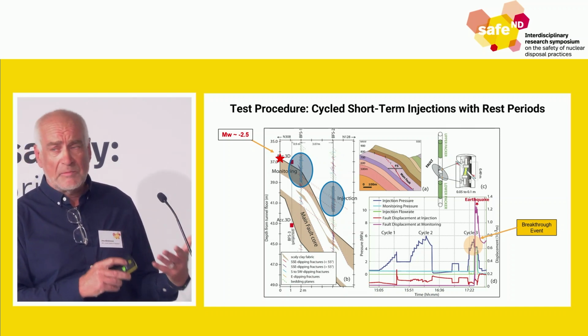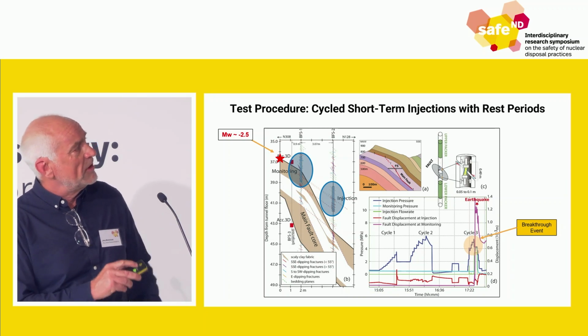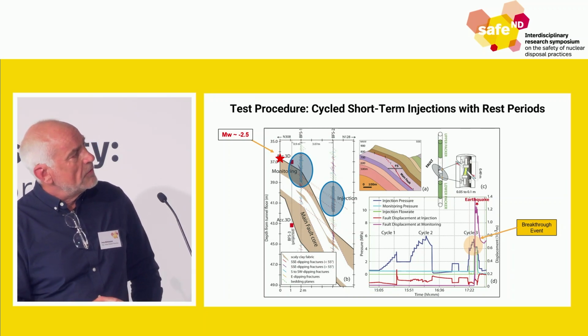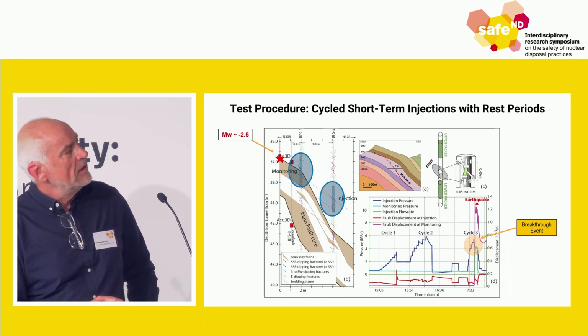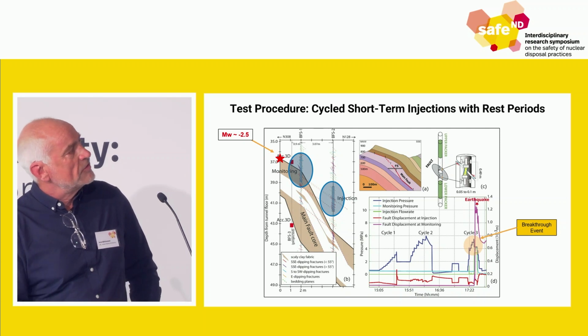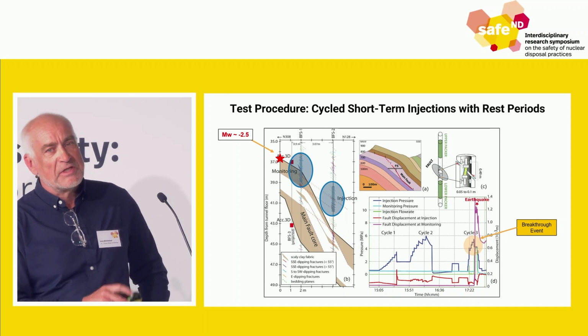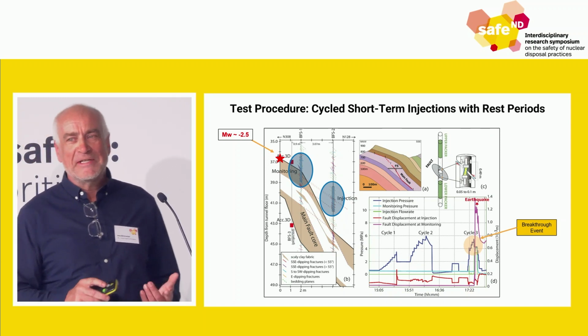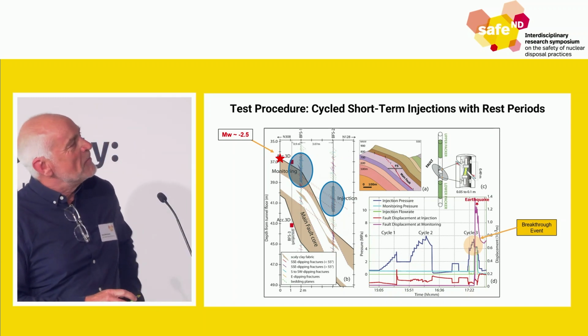Initially there was almost no permeability in that fault. We got a breakthrough shown here. These are displacements in the injection chamber, so tiny displacements here, nothing in this monitoring chamber, then suddenly it shoots up. And in fact, a little later, we generated a minus 2.5 earthquake, which we didn't quite expect.